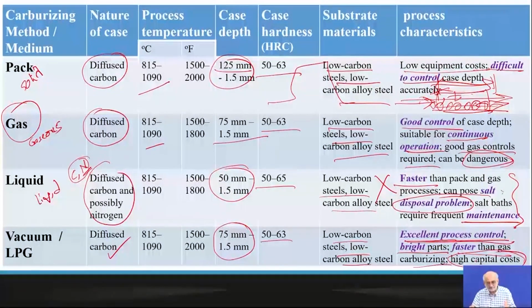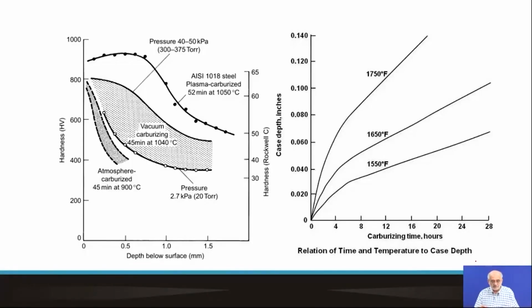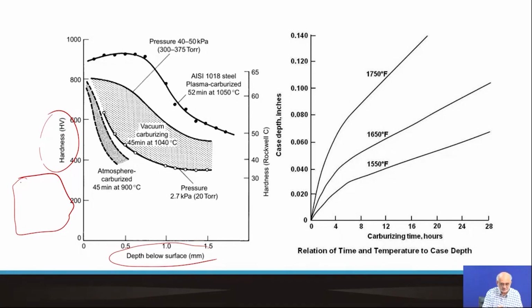So this is typically the hardness distribution of the stock after carburizing. So this is depth. Again, let's say this is the specimen we are talking about. This is the case that we have created, and this is the depth that we are talking about. From the surface into the inside, this is how the hardness varies with depth, and we can see that up to a certain depth we maintain reasonably high hardness. The hardness can be very large. We don't necessarily need such very high hardness.